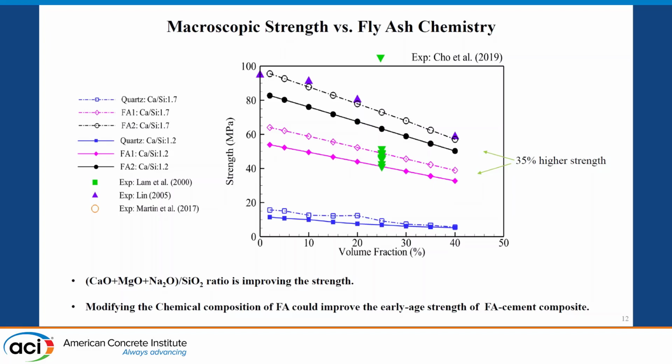Okay, so the conclusion would be that, based on all our observations and all our modeling strategy, whenever you are thinking about increasing the strength of the fly ash cement system with this type of fly ash, type F, which is slowly reacting, then if you experience a higher concentration of cations and alkalis, most likely, and all the results point to that, you have a higher interfacial strength, higher stiffness of the interface, and this will lead to increased uniaxial compressive strength. So that's the main result.